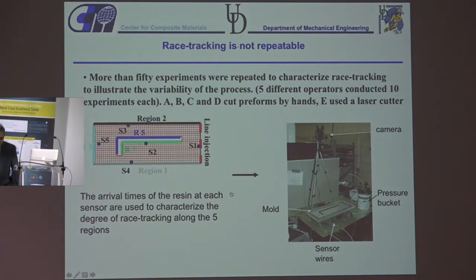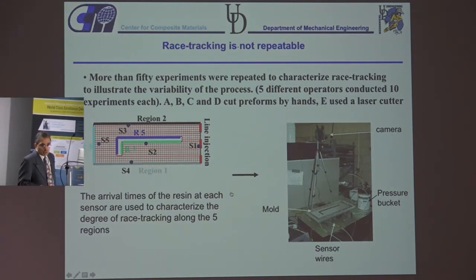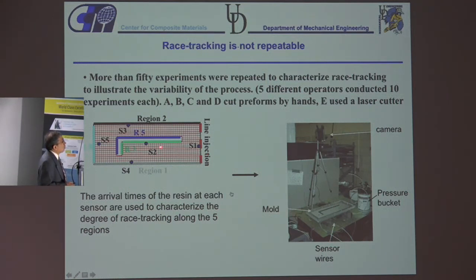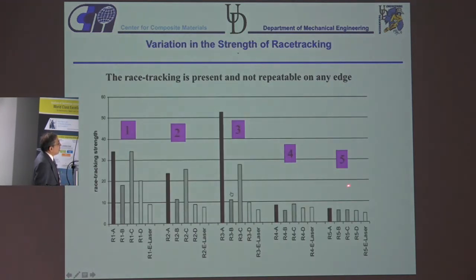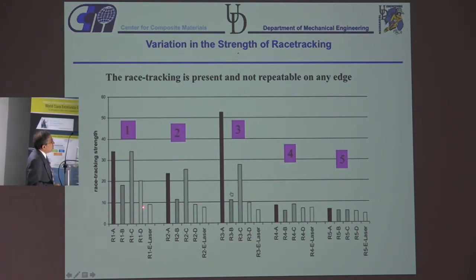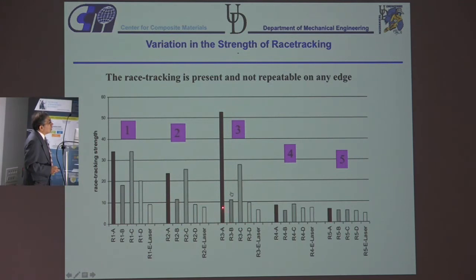So I said, okay, is race tracking something that is predictable? This is the advantage of being in academia, that I had 5 students do 10 experiments each, where there was race tracking along these 5 edges, 1, 2, 3, 4, 5, and we injected from the 2 sides, and here is the mold, and we had sensors in different locations to see when the resin arrived there. And here are the results at those 5 edges by the 5 students, and this is the average of their 10 experiments. So at each edge, the race tracking was different for each student, and you could probably look at this and see which student was more careful and which student was less careful, but this is the average of 10 experiments. It's not just one experiment that they did.